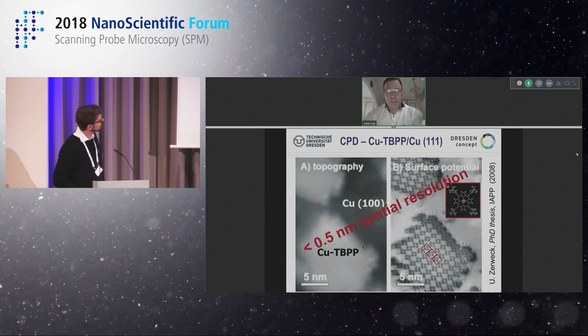This is simply because the Q value of the cantilever goes up when you go into vacuum, and hence you get even a better resolution for your Kelvin, but you can also use, for instance, artificial Q control in order to increase the Q value. So there are many different methods, but the temperature is not low temperature, it's room temperature. So would that mean we can overcome some of the limitations we have for topography imaging when we use the Kelvin probe method to analyze the surface? That's exactly one of the bottom messages. One thing is, first of all, go for FM and then use also Q control, exactly.